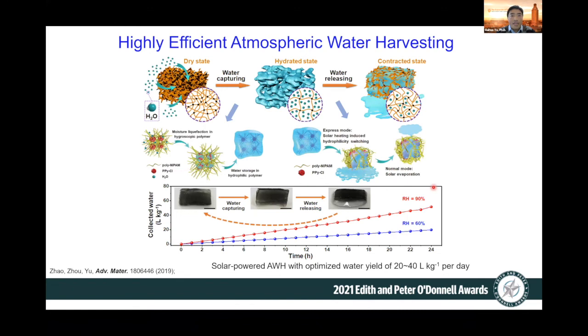And this is the mechanism I'm going to show you quickly. Basically during water capturing, the hygroscopic polymer can absorb the water vapor, and due to internal water transport between the hygroscopic polymer and the NIPAM, they can have better storage capacity. And with a mild temperature change, for example, by mild sunlight, you can effectively induce the release of the water by this hydrophilicity switching, because of their lower critical solution temperature, they can change from a hydrophilic state to a hydrophobic state, so they can release the water effectively. So in our optimized design, every hour, you have 15 minutes of absorption and 10 minutes of release.